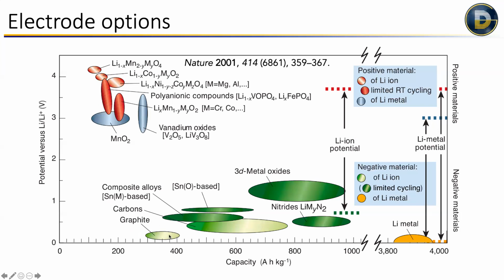And there's a lot of reasons for this, but the biggest one is that it's very reversible. You can put lithium in and pull it out because it's layered. So the reason why we can use graphite in our pencils is because it's got this layered structure, and those layers can come off. Well, in the case of an electrode, we can actually shove lithium ions in between the layers and then pull them out without damaging the graphite structure too much. And we can put a lot of lithium in, relatively.